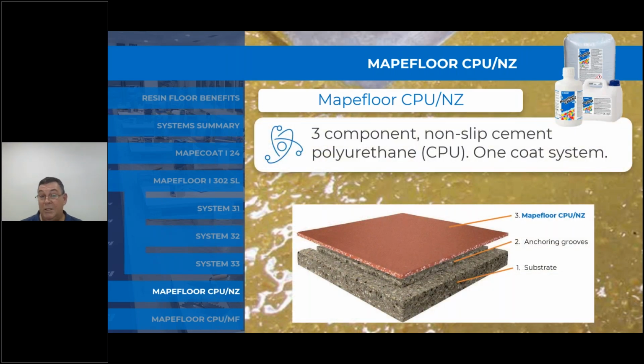So onto the Mapefloor CPU NZ, it's a 3-component non-slip cement polyurethane 1-coat system. So this system only requires one application. The substrate needs to be obviously prepared, but it can be damp, can have moisture in it. It's imperative that every CPU, cement polyurethane floor, has the anchoring grooves, and I'll explain those a little bit further in the slides ahead. But the anchoring grooves, and then the Mapefloor CPU NZ is applied as a single coat between 4 and 6 millimeters across the floor. So this system is in and out the same day. There's no waiting for primers to dry and moving on to the next step and the next step. It's preparation of the floor and installation of the floor in one step.